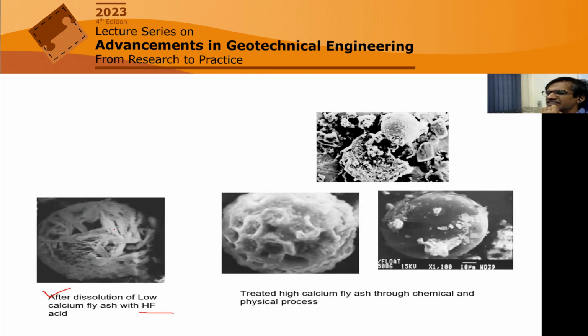So this indicates that the top surface is reactive and it can react. Whereas in some other fly ash, in fact, this was rich in some iron particles. So this one, it was not taking part in reaction, whereas the small patches you were seeing were taking part in reaction and they were being utilized for cementitious use, or because this was high calcium fly ash, it can be used as cementitious or pozzolanic both. But in this case, it is only pozzolanic top surface. So this material characterization through morphological identification is important if you want to really study its utilization.